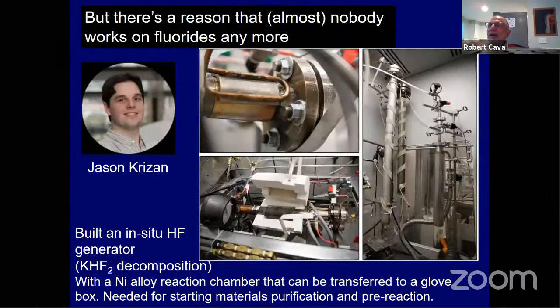And then I had this character here, Jason, who was one of my graduate students. I remember one day said to me, I want to make some of these fluoride pyrochlores you're talking about, but I need to buy a tube, a metal tube. So this tube right here. And the reason he needs to buy like a nickel metal tube is because nickel doesn't react too much with fluorine. And he needed to do an in situ HF anneal, hydrofluoric acid, anneal, hydrofluoric vapor to clean out the